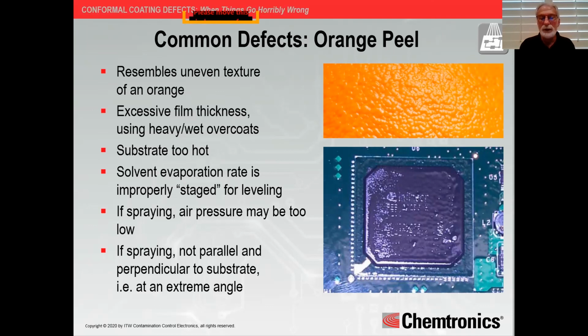If your substrate is too warm relative to the temperature of the coating, it can cause this. Let's say you just cleaned your board, it's gone through the dry cycle in your wash system, you take it out and it's still warm, but you're in a hurry and your operators need to coat it. Well, now they're applying this coating.